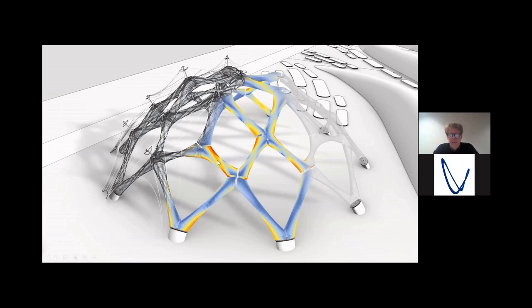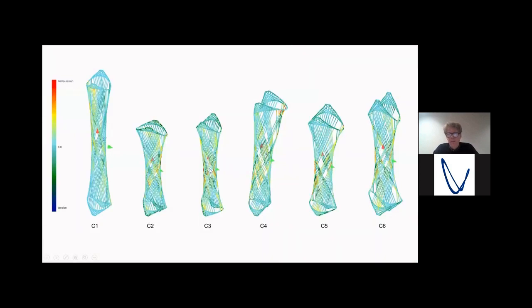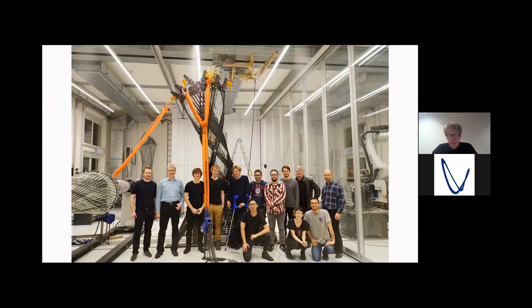We also have models to calculate and analyze the loading in the respective fiber bundles, but what we cannot do is reliably predict the failure load of the components. So we are still relying on a larger series of large scale testing.